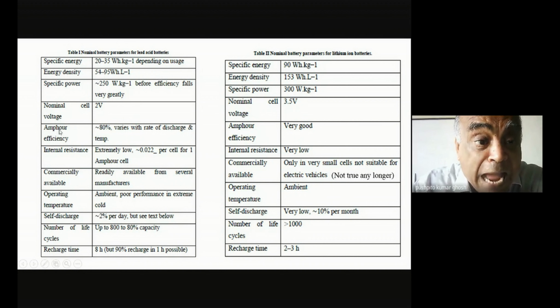Okay. Now, the ampere-hour efficiency is comparable, very good in all the cases. The internal resistance, because this would be a loss, and also it will lead to heating up of the cell if your resistance is high. It's very low here, and also very low here. I don't think there is much of a gain in terms of internal resistance. Commercially available, yes. Today they are commercially available, at least for mobiles and things. For electric vehicles, not really, because they are way too costly at present, compared to the lead-acid batteries. Operating temperature of both are ambient.